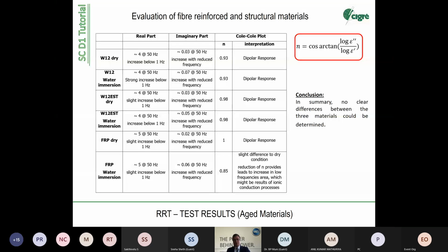And also we see the impact of water. FRP, water immersed, is lowering N, which means we are starting a conduction process. So we can see very well here with the N evaluation whether we are becoming more conductive inside or whether we are starting a more ionic conduction process. Ionic conduction, by the way, in most electrical materials is the starting point for compromising or lowering the electrical strength,